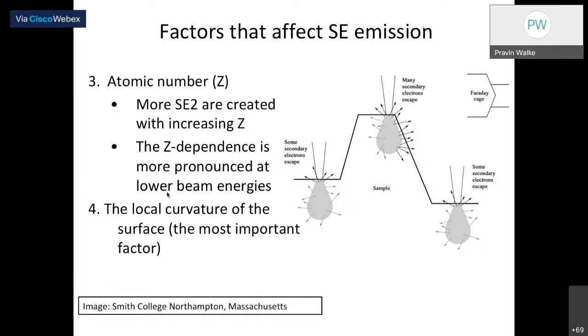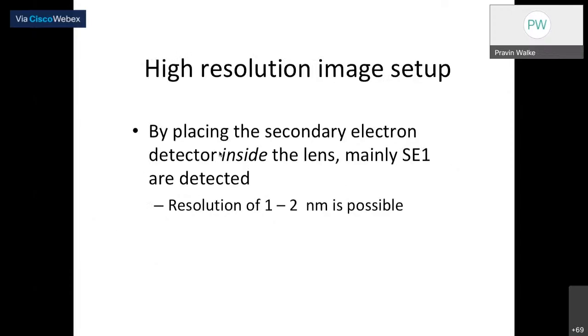Also, another important factor for the SE emission is the local curvature of the surface. If your surface has a sharp curvature, then the topmost surface SE emission will be very high. The pointed surfaces will give you good SE emissions, right? So these are the important factors which we need to understand about the secondary electrons, right?